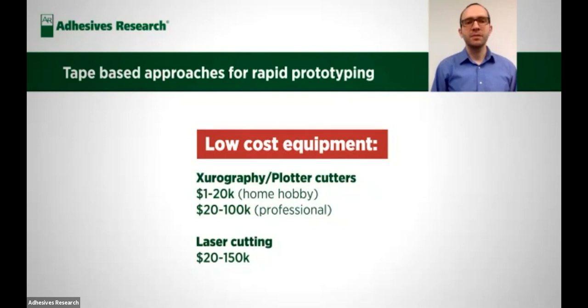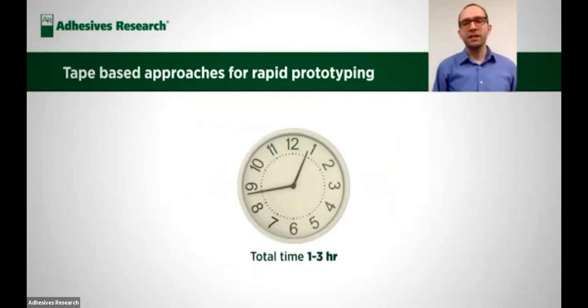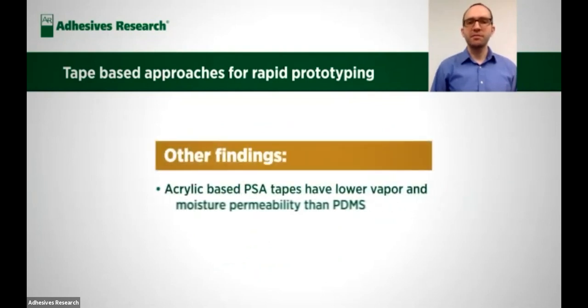these microfluidic channels. And I think an even better advantage is the total time spent between designing the AutoCAD file to producing your microfluidic device and disinfecting it is a total of 1 to 3 hours, which is substantially lower than what is required to access the microfabrication facilities and produce the full device through soft lithography. Other interesting findings are that acrylic-based PSAs were found to have lower vapor and moisture permeability than PDMS, which for certain applications such as organ cell growth is very important. You don't want to have very high moisture permeability.